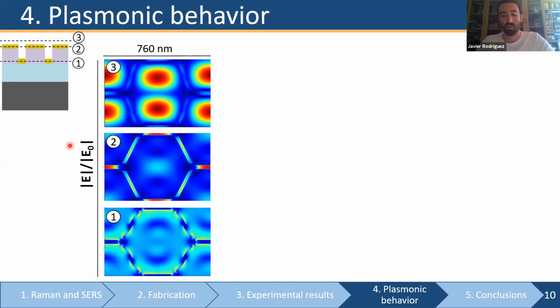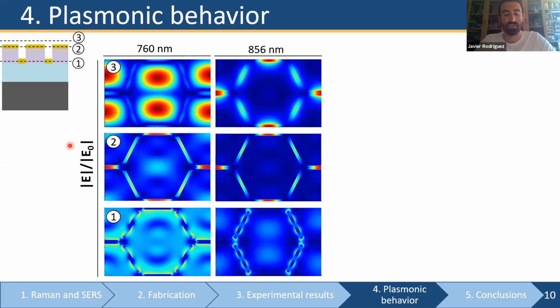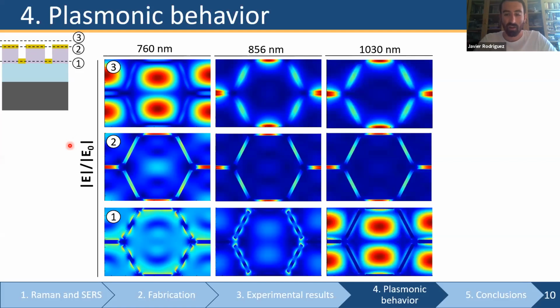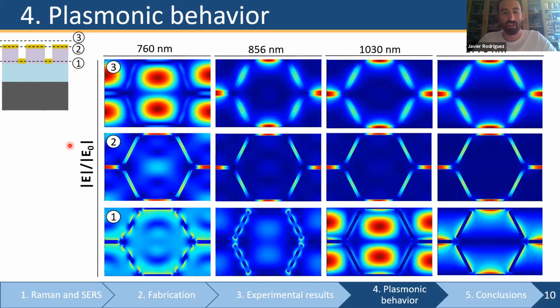So for the sake of completeness, if we take a look at the near field at other peaks, we can see a wide range of interactions. But all of them are of a more localized nature. All of them except for this one, which is again collective. So we can see that we have 2 collective excitations of this structure, one at 760 nanometers, and the other one at 1030 nanometers.